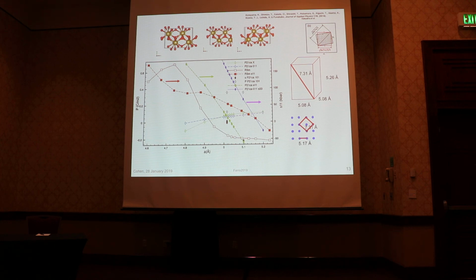And the other thing is that many of them have the polarization in the plane. So if you're measuring thin films and you're not set up for that, you might think you don't have a polar structure, but it's just that the polarization is perpendicular to the direction you're measuring. And in many cases the polarization ends up being oblique. So even if you're measuring the c-axis polarization, you're only going to pick up a part of it. So that's interesting to me as well.